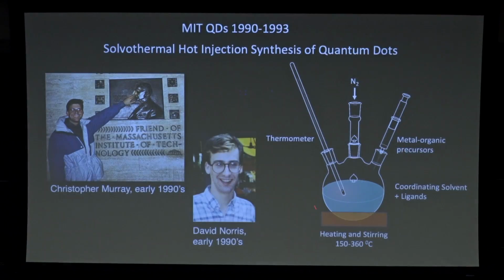So it was very simple. You put a solvent with some coordinating ligands. You have your organometallic precursors. You heat this up to whatever the temperature is for that solvent and their ligands. You quickly inject your precursors. That forms little seeds. That's your nucleation.